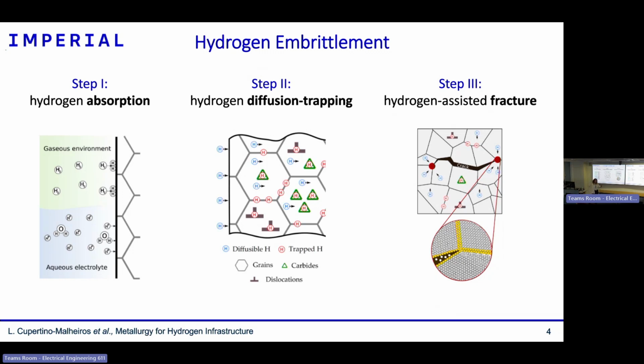Okay, once hydrogen is inside, in the bulk of the material, the second step is hydrogen moving inside of the material, of the metals. And hydrogen will move relatively fast, even at room temperature, which is called the diffusion phenomenon. And specifically, hydrogen will also interact with the structure of alloys. So whichever type of defect of this crystal structure, the structure of alloys, have positions where hydrogen can be more stable, it tends to accumulate in those areas, and this phenomenon is called trapping.